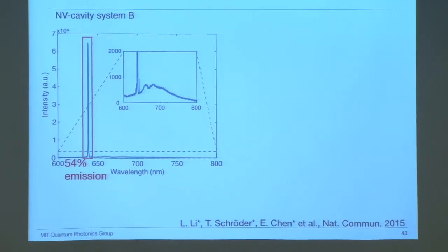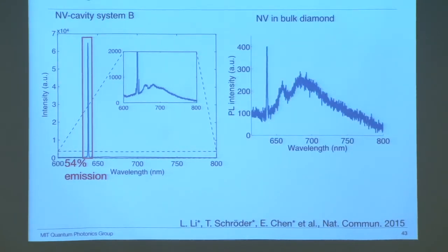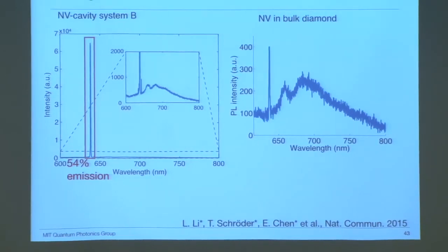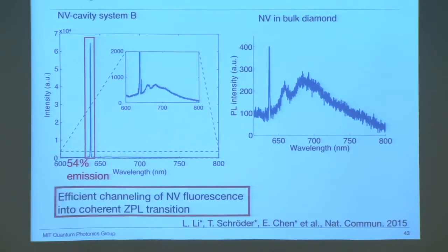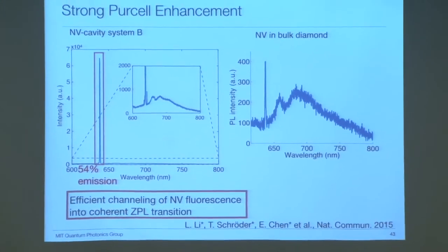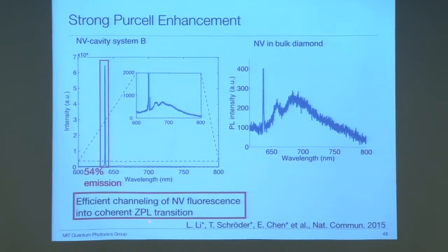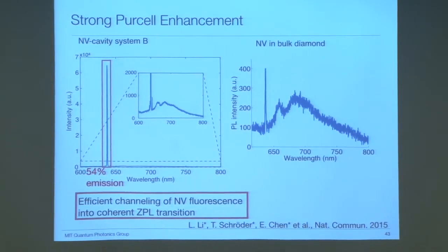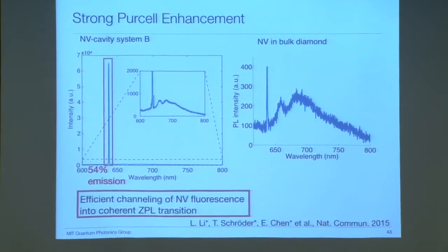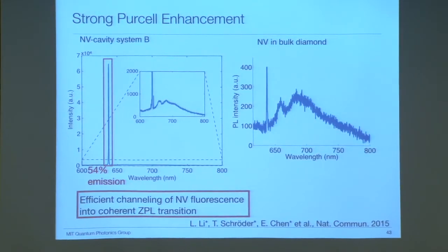As a reminder, this is a spectrum of a native NV inside a bulk diamond. The NV ZPL only occupies 2 or 3% of the overall emission. And this NV cavity system B efficiently channels the NV photoluminescence into the coherent ZPL transition. This bright line is exactly what we want as an efficient spin-photon interface for building quantum networks.